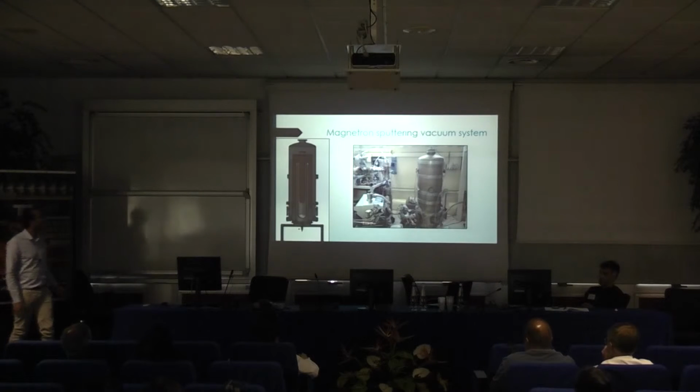We decided to use the magnetron sputtering technique. That is a very well-known technique. It has a main advantage, the higher deposition rate in comparison with other processes. But it also has a main disadvantage, the erosion of the material is not so uniform. So that was our challenge.